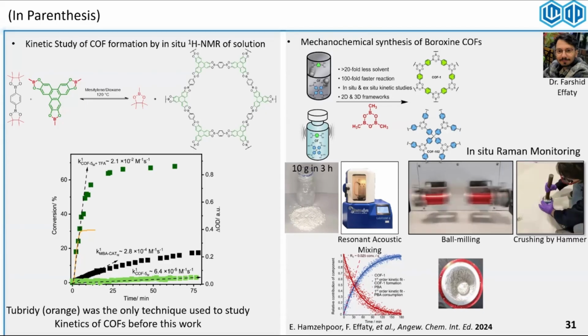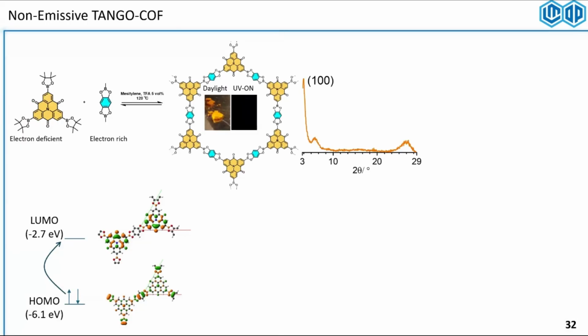But we also used the same methodology to make mechanochemical, solvent-free covalent organic framework formation. And we studied many different techniques. We found that even just crushing the powders with a hammer, sort of like a caveman, it forms the covalent organic framework for us. So we don't really need very fancy techniques like ball milling and RAM to make COFs solvent-free. Long story short, we went back to the original idea. Now we were able to make the Tango COF.